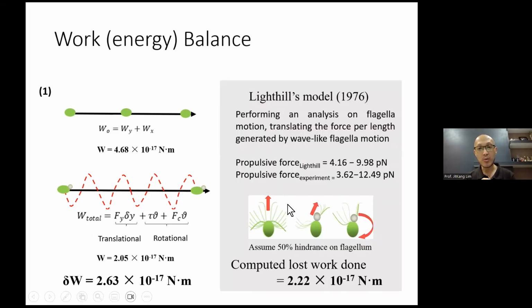And we use a mathematical model proposed by James Lighthill many years ago. We compute by assuming 50% hindrance of the heterogeneity. That means we assume one part of it can't move, and there's only one, like what I showed you just now, that moves healthily. And we managed to compute a work loss of about 2.2 times 10 to the power negative 17. And these two numbers are in quite good agreement. This reconfirms that the reason why we observe a slowing down and loss of work is because one part of the flagella is suppressed in its motion, and eventually this couldn't drive the whole construct to move healthily. That's also the reason why it goes through helical motions.